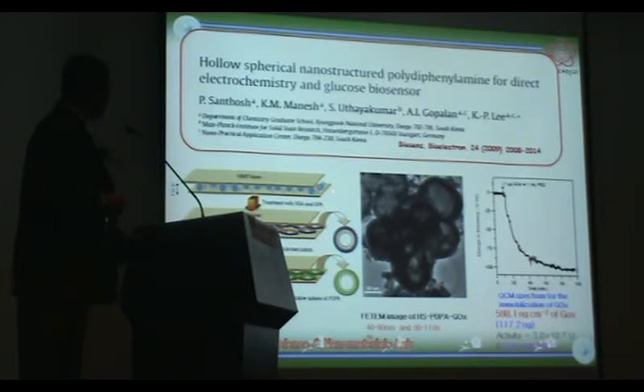So this is one research we have published in Bioelectronics, and here we have utilized hollow spherical conducting polymer nanostructures for the immobilization of GOX. We prepared these hollow spherical polydiphenylamine nanostructures by using a soft template assisted self-assembly approach. We prepared them within the gallery of the MMT clay. A mixture of the monomer diphenylamine and beta-naphthalene sulfonic acid was allowed to self-assemble within the gallery, and after that it was allowed to polymerize. Once the polymer is formed, it was extracted, and because beta-naphthalene sulfonic acid was used as a soft template, it can be removed, and you get a beautiful hollow spherical nanostructure.